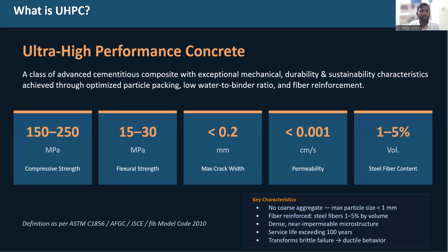It also has less permeability because of its dense packing and material composition, as very fine materials are used in the preparation of ultra high performance concrete. That leads to lower permeability. And in order to attain this flexural strength or tensile capacity, it is essential to use steel fibers. That's how ultra high performance concrete is prepared. The typical percentage is around 2%, though we can extend it up to 5%. But anything beyond 2% will lead to workability issues and negative effects on compressive strength and other properties. So this is, in simple terms, what ultra high performance concrete is.